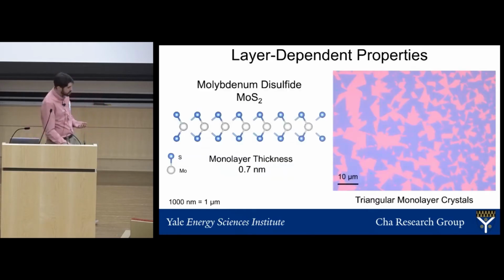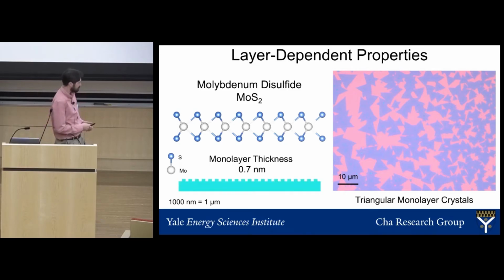So for example, this is molybdenum disulfide. This is a material that I study. So it's formed from a molybdenum atom bonded in between 2 sulfur atoms. And each monolayer is only 3 atoms thick, and it's actually 0.7 nanometers thick. And if we take a single layer, one single Lego brick of them, they actually are purple in color.